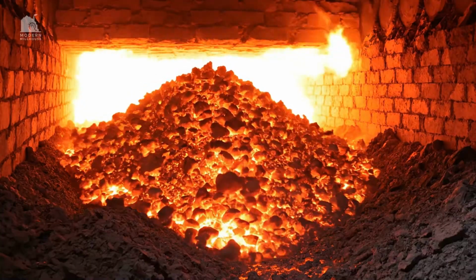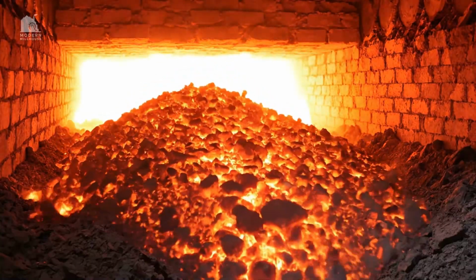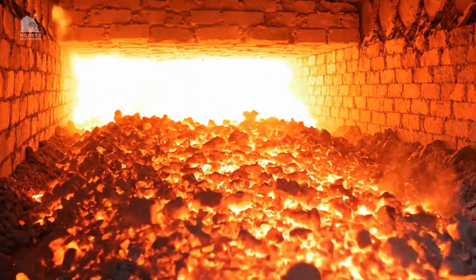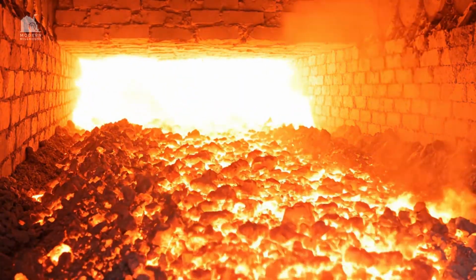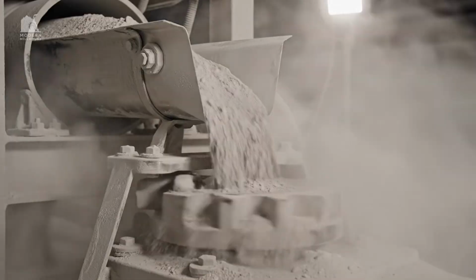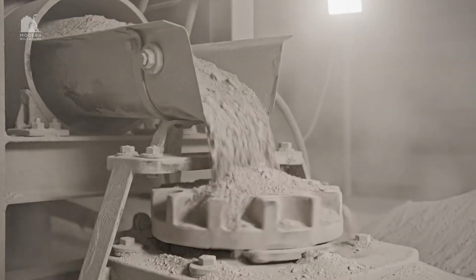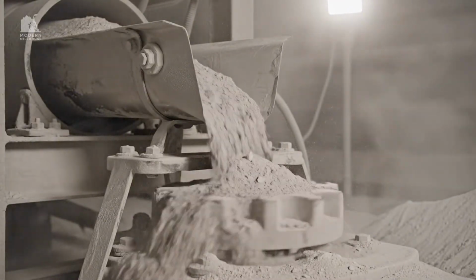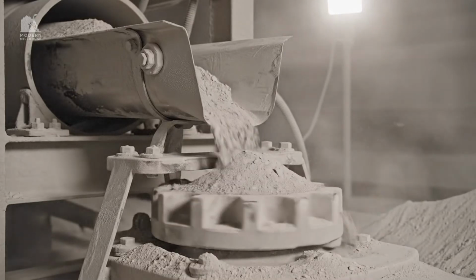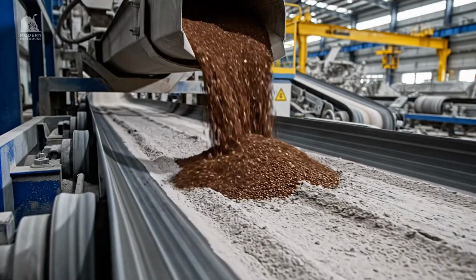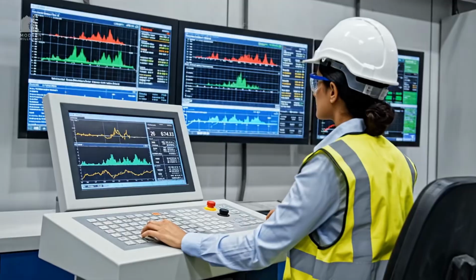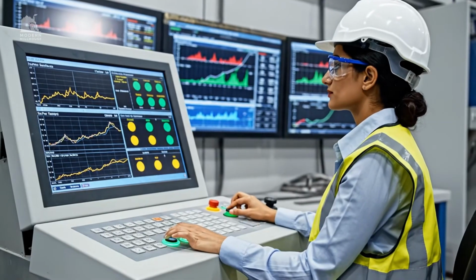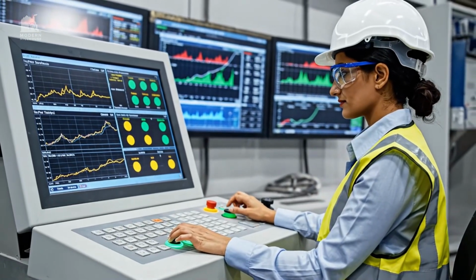Feed rate affects bed depth and heat transfer. Too much feed can cool the flame zone and underburn clinker. A consistent feed avoids temperature swings, which otherwise create variable clinker quality and increased fuel use. Minor corrective additions can stabilize the melt phase, helping clinker form properly without excessive buildup.